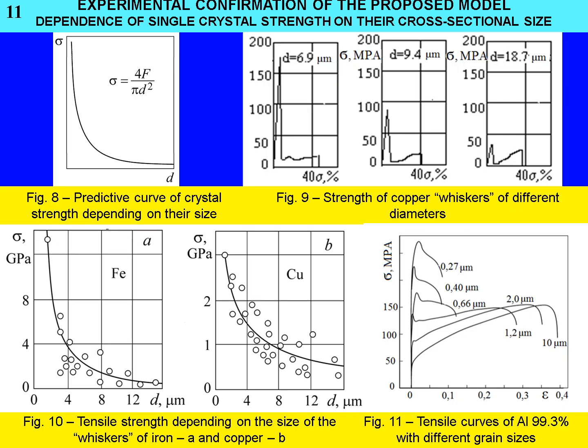First confirmation. Slide 11, Dependence of single crystal strength on cross-sectional size. According to the proposed model, the strength of a plastic crystal is determined by the strength of its surface layer and therefore depends on its cross-sectional size. For small diameters, the yield stress should be high and decrease with increasing diameter, following the predicted curve (figure 8, slide 11). This prediction is supported by experimental data (figures 9 and 10).